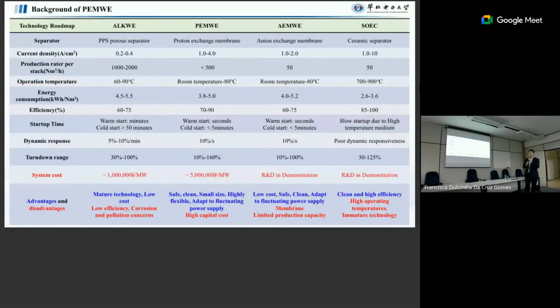Then the AEM is very similar to the PEM system in structure, because here they use an anion exchange membrane. But the biggest difference is that instead of water, they use alkaline solutions. And this solution has OH ions, which can attack the membrane. The lifetime of the anion exchange membrane at the moment is very short. So it limits the use of the system. And also, the current is limited. Here it's rated 1 to 2. In my opinion, it's less than 1 at the moment. It's difficult to reach a high current density. Nowadays it's still in R&D demonstration.